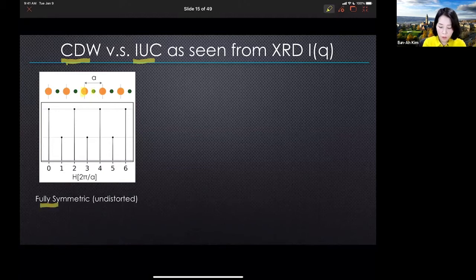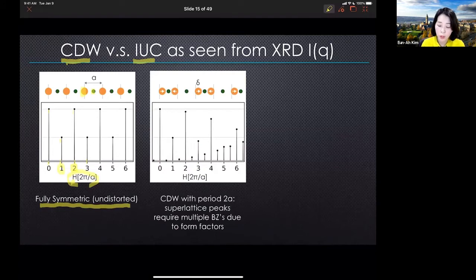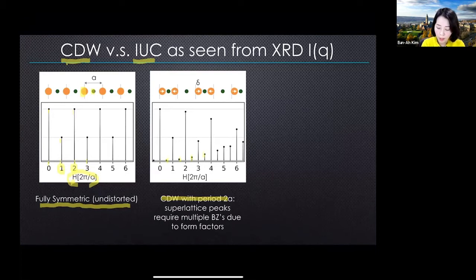In an undistorted state, my X-ray intensity looked like this. This is in reciprocal space. I have Bragg peaks, which are affected by the form factor, and I have a peak at every integer position. Now, if I develop a charge density wave, which changes the size of the unit cell, in this case, the unit cell size has been doubled. With the doubling of the unit cell, with the charge density wave of period 2a, the new phenomenon that emerges is these peaks at half integer positions. These are superlattice peaks.